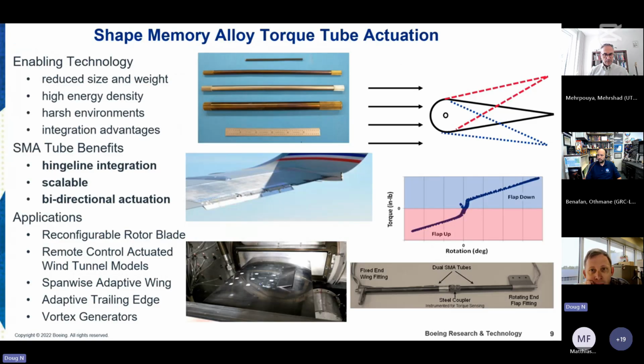A little bit more recently, and driven by one of our commonly used forms, is shape memory alloy torque tube actuation. So a lot of the benefits on the first slide, with the additional benefits of having a tube: we can have a rotary actuator that has high energy density that I can integrate into a hinge line. It's scalable. Unlike wire, it has bidirectional actuation, so I could put a two-way shape memory effect in there and get, for example, flap movement up and down. And it has a lot of applications that we care about. Here I'm showing ones for aerospace, such as actuated wind tunnel models and the adaptive trailing edge that we tested in flight.